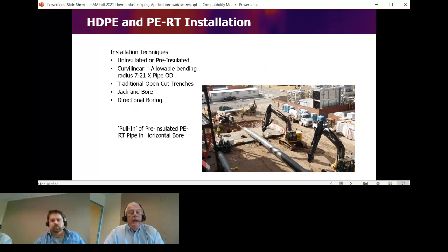HDPE and PERT are available in uninsulated and pre-insulated versions. Selecting a pre-insulated version also depends on how you're going to install it. Often when you do a directional boring, you increase the jacket thickness just to allow for a little bit more abrasion as you pull the pipe through. You can use curvilinear alignments, both horizontal and in a boring, dipping down and raising back up. In the picture on the right, they're crossing under a building and the foundation of a tunnel, because of a sequential requirement of the project: the lines had to be put in before the building and the tunnel were modified. Otherwise, you can install by traditional open cut, jack and bore, and, as I mentioned, directional boring.